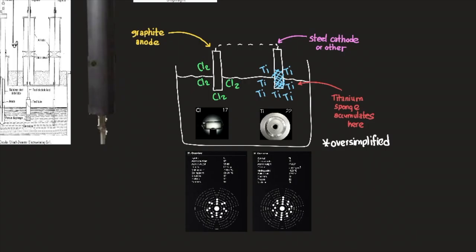A different process that offers hope for an improved and simplified method of producing titanium metal is the direct electrowinning of titanium from TiCl4 in fused chloride salt baths. In this case, titanium sponge collects on a steel cathode and chlorine gas is given off at the carbon anode. The required use in this process of high melting point salts, combined with the need for maintaining an inert environment, present major technical and economic hurdles that have to be overcome in order to achieve commercial status.